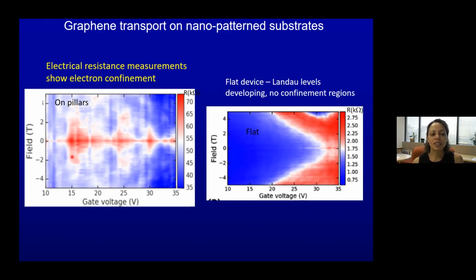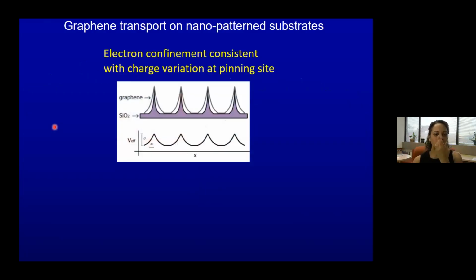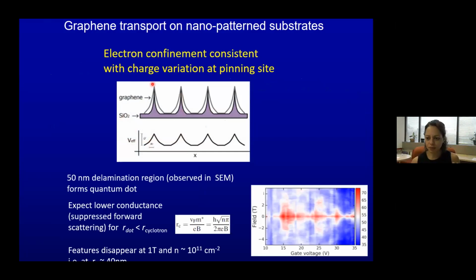And we believe that these high resistance regions are due to the strain and the pinning of the graphene on the pillars. Okay. And in fact, we can show that just the pinning alone can lead to some sort of charge variation. So you get a tenting of graphene and this potential difference across the device. And we can show that we expect decreased forward scattering for small regions of confinement along the apex in cases where the path is smaller than the cyclotron radius in the field. And in contrast, a higher field will focus carriers and enhance conductivity. And so we actually see that we have confinement.